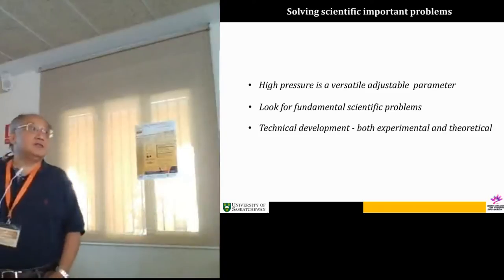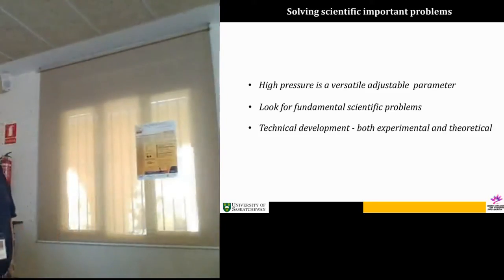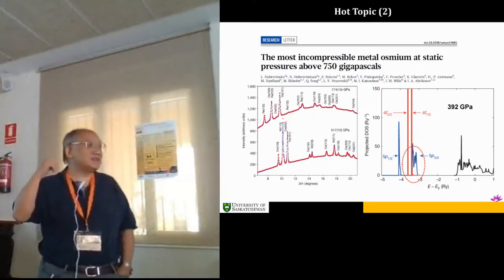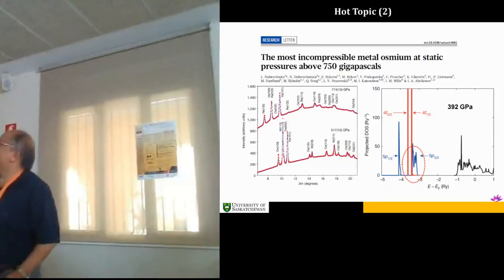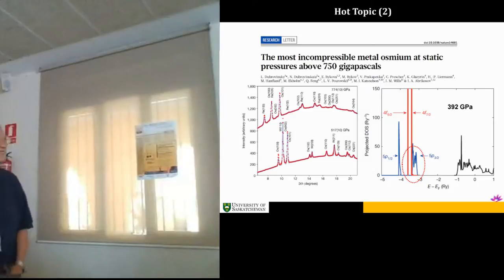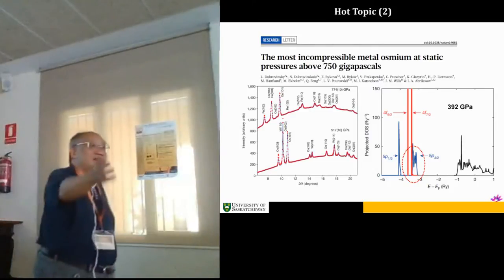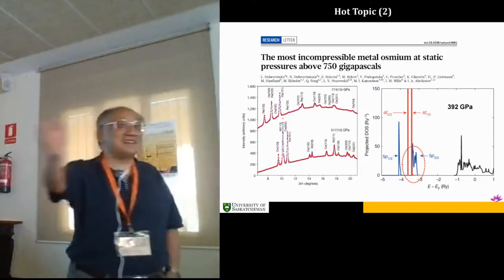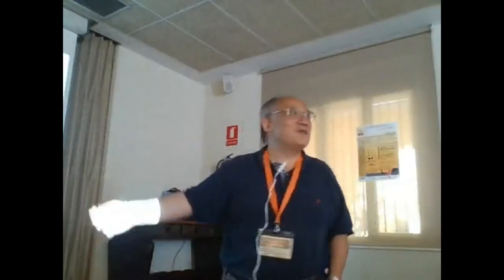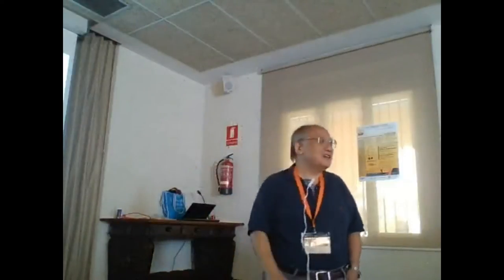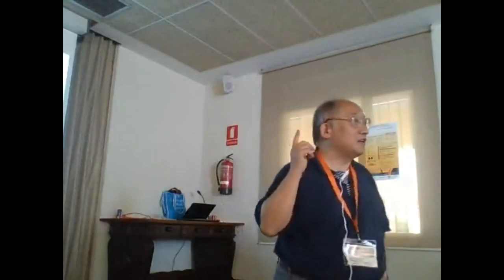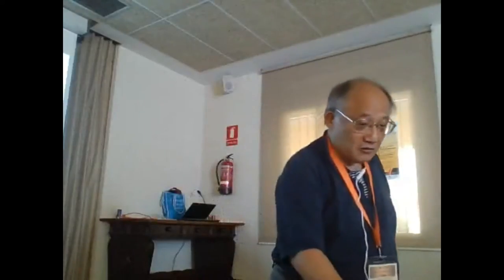All this development I show you in the two papers is all because of technical development. The reason they have this diffraction pattern, you know what's the size of the sample? The micron. So the beam has to be micron or submicron. What's impressive, you look at something there called Re, right? Everybody who does diffraction will know that. That's the gasket. Now look at the gasket peak, it's so small. So you know how small the beam is. It only hit the gasket a little bit. Of course, the development of the diamond cell is an important contribution, but the technical development of the synchrotron diffraction here is impressive.